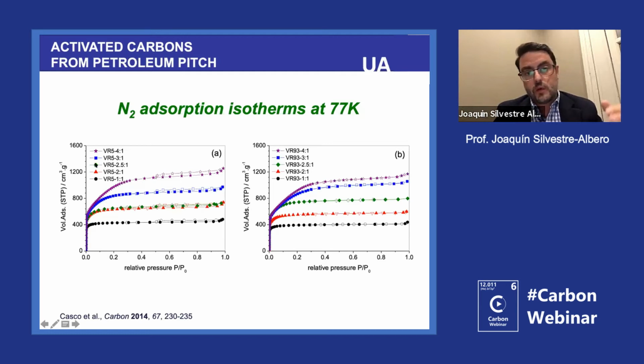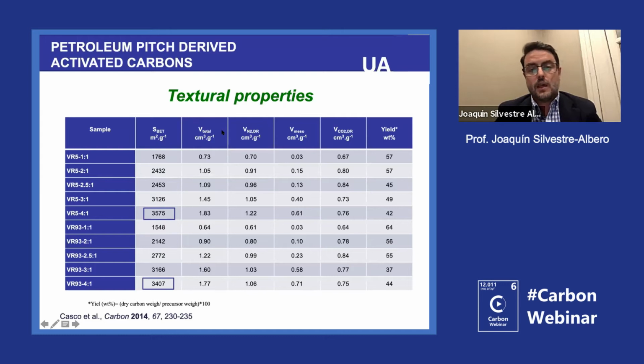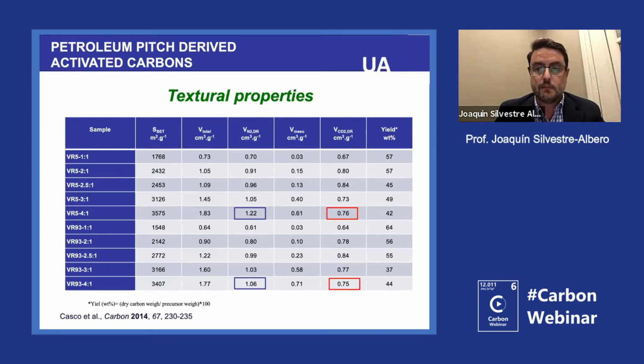When we were increasing the amount of KOH to 2, 2.5, 3, 4, you can see that we are increasing the porosity. We are also widening the micropores, and we are also developing a small amount of mesoporosity. And as I say, the performance is rather similar in both cases, independently if you have a low or a high mesophase content. We did an evaluation of the textural properties, and we were able to see that when you are activating the sample with 1:4, you can reach up to 3,500 square meters per gram. So this is a very significant surface area for a carbon material.